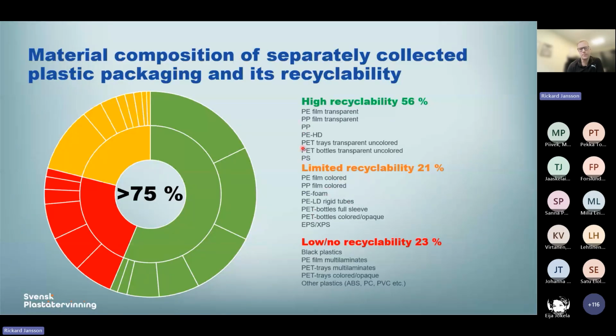But rigid plastics, which are up here, typically end up in high quality applications. For example, clear transparent PET bottles go back to the bottle industry. While if you are down here in the limited recyclability, it means that often the materials that get recycled will not end up in the packaging industry. They will be used in other industries instead. And if you are down here in the low or no recyclability, the quality of the recycled materials is very low, meaning that they either go into these composite materials that replace wood, or they are not getting recycled at all.